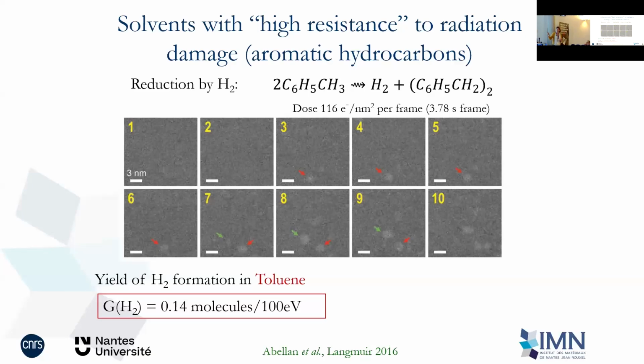Yeah, in this case, I used toluene, and something that is important if one day you want to use this table is that you need to control the oxygen, because oxygen is also a scavenger in many cases. All these numbers that they give in radiation chemistry assume that you are controlling your environment. Otherwise, they would add oxygen. But usually we do the loading and there is oxygen in there, and this has to be taken into account, or you need to buy a glove box for aqueous solution for the oxygen.